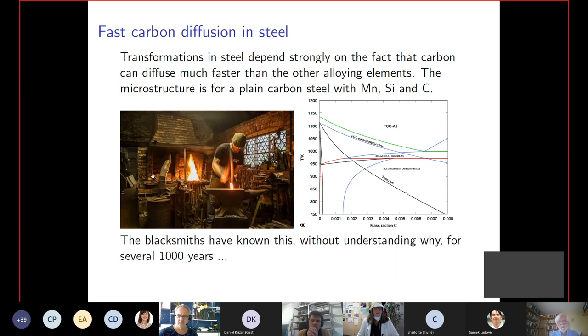So this has been known for a long time, but of course they didn't really understand what they were doing, except that you get a good result from varying the heat treatment and varying the cooling temperature. And this you do just with thermodynamics. You have basically no kinetics, except that you assume that carbon can diffuse much faster than the other elements.